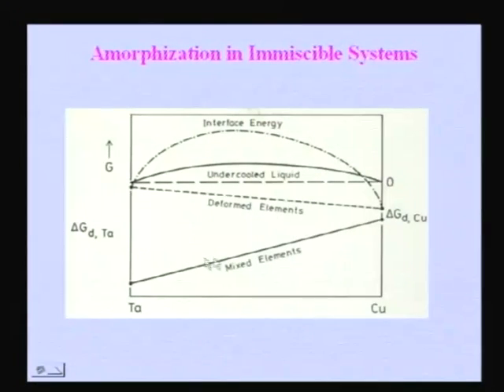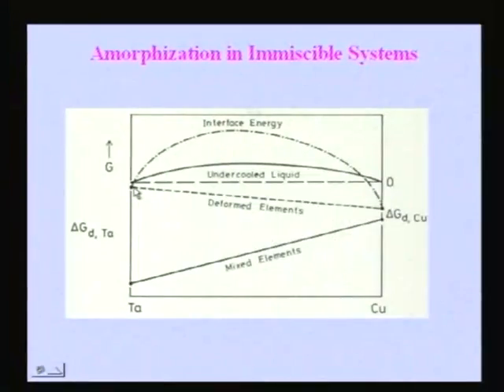And if the free energy goes like this, when you deform the individual metals, depending on the type of metal, copper cannot be easily deformed when compared to tantalum. Tantalum has a higher melting point, so you can make it nanocrystalline much more easily. As a result, it becomes finer much more easily, so its free energy goes up to a much higher level than the free energy of the copper going up.